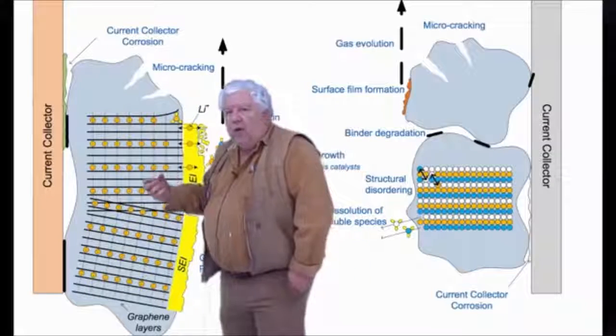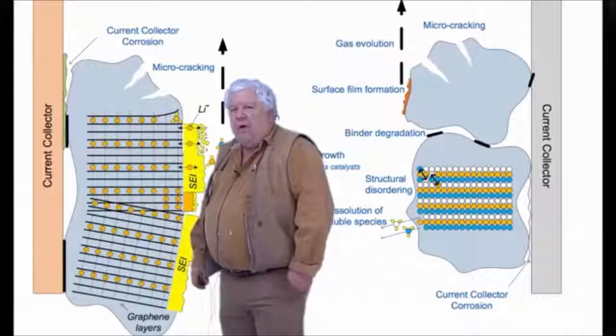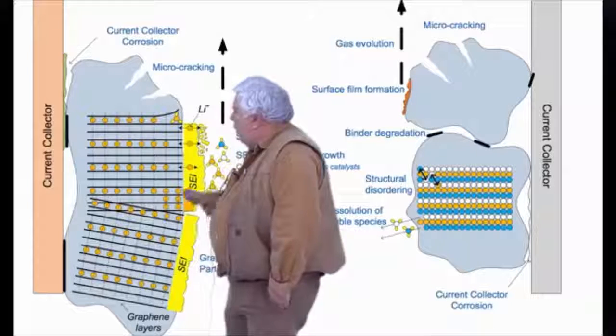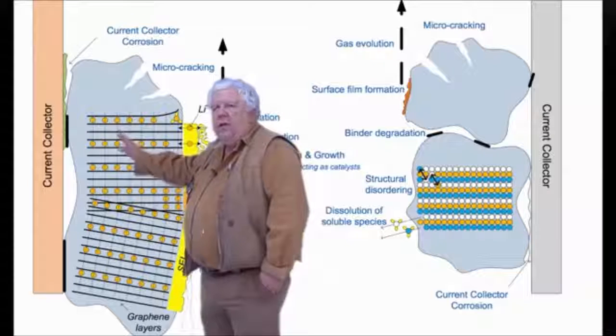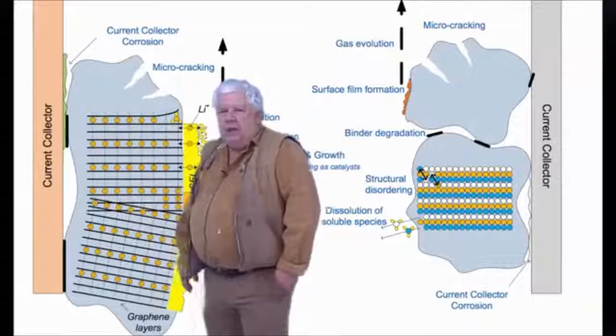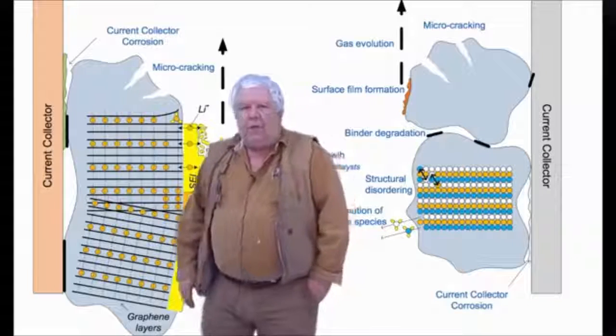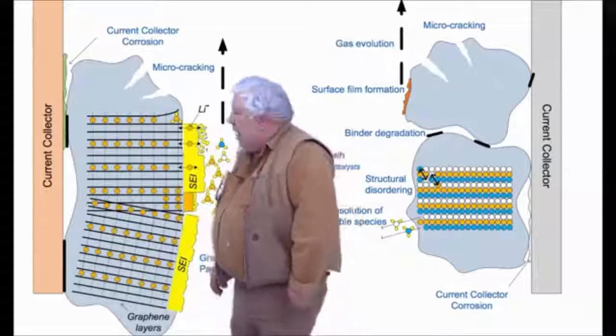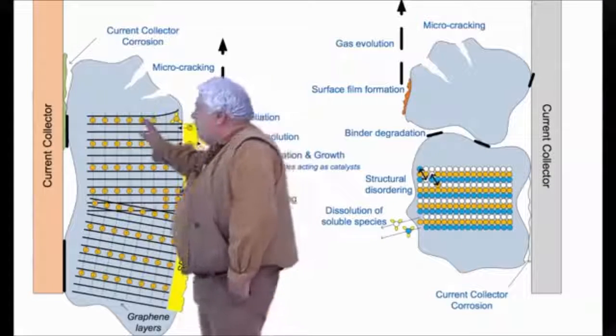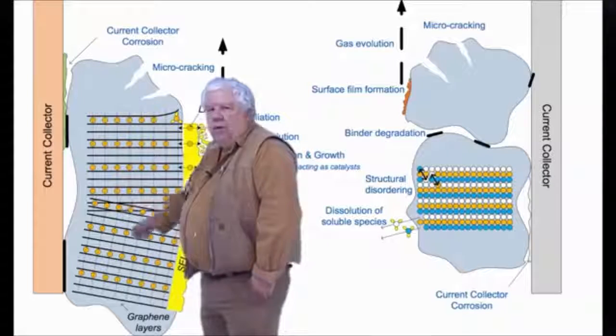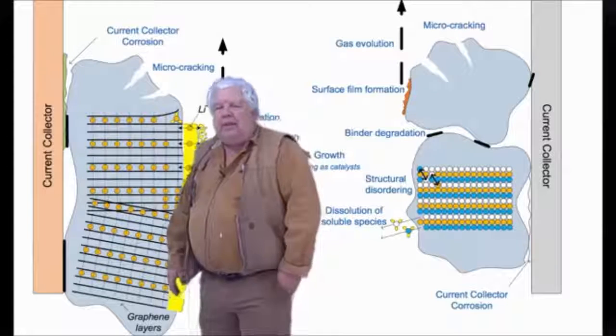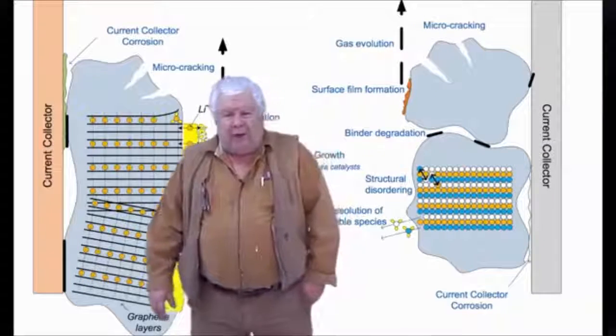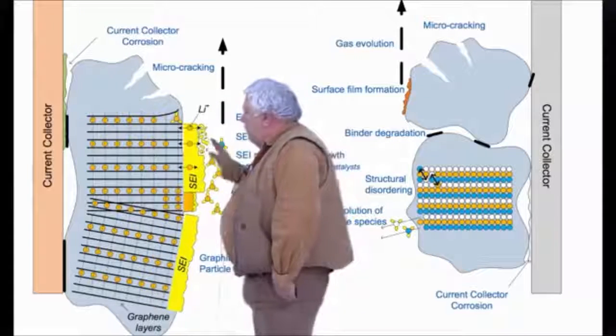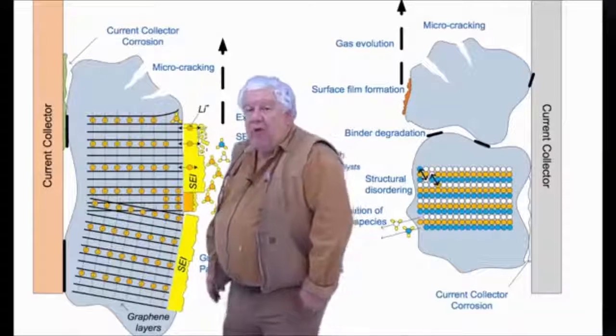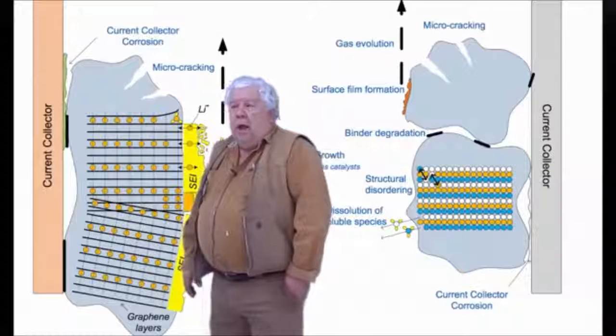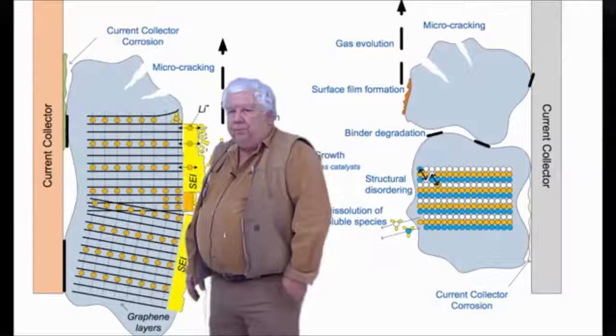They're held in position now. They're going to come in contact. And that gives off heat. At between 110 and 130 degrees centigrade, the SEI layer starts to come unglued. It starts to melt. It's coming apart. And as it comes apart, here is this huge treasure trove of lithium ions, fairly suddenly exposed to these solvents and reacting with them and generating heat. And we go into thermal runaway.